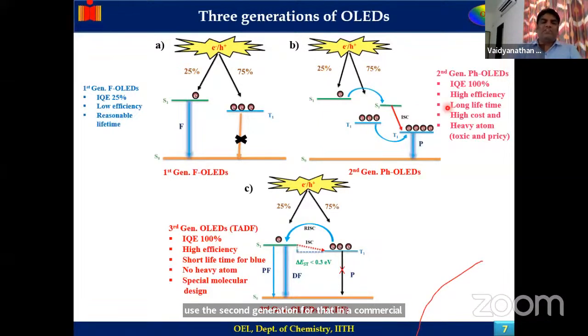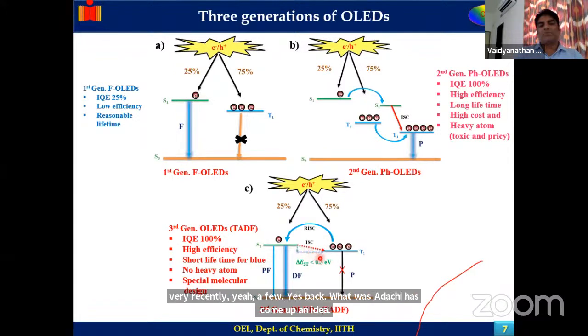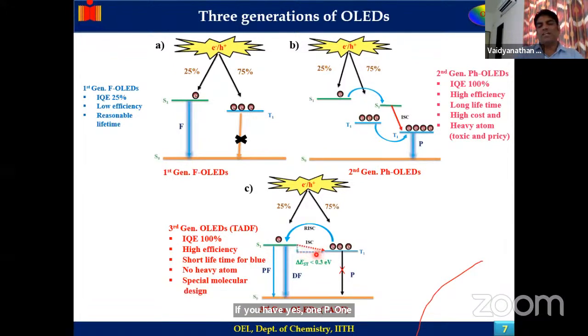Okay, very recently, a few years back, Professor Adachi came up with an idea. If you have S1 and T1 states with a marginally smaller gap, that means less than 0.3 electron volt, then room temperature is sufficient to harvest this energy to the S1 state by reverse inter-system crossing.